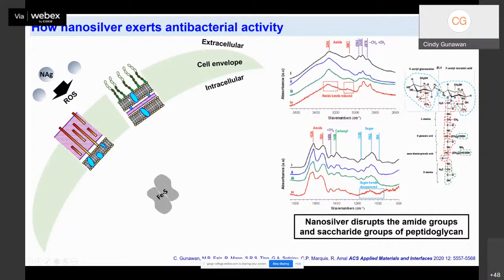Here with our ATR Fourier transform infrared spectroscopy, or ATR-FTIR, we have shown that silver nanoparticles can disrupt the peptidoglycan layer in bacteria. So the peptidoglycan layer is basically a polymeric chain of amino sugars. It is an alternating polymer chain of N-acetylglucosamine and N-acetylmuramic acid linked by beta-glycosidic linkages, and this polymeric chain of the amino sugars is interlinked by peptide chains. And our infrared spectroscopy has shown that nanosilver can actually disrupt the amide groups that are present in the peptide chain here, as well as in the amino sugars here.